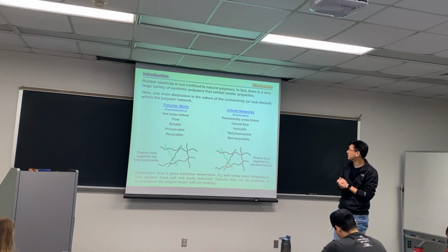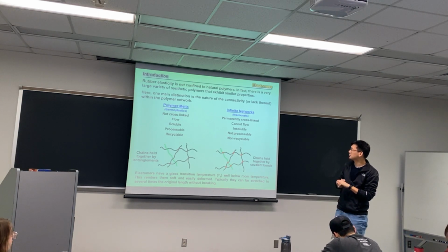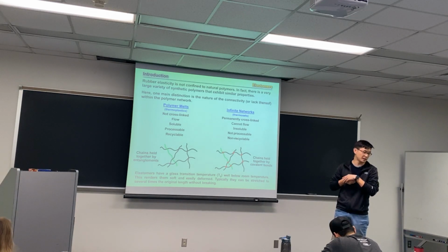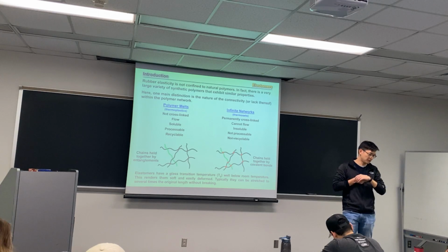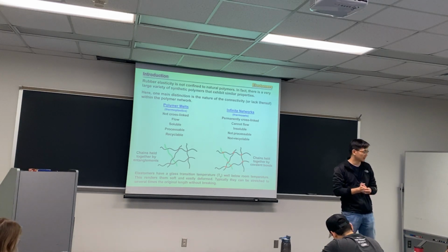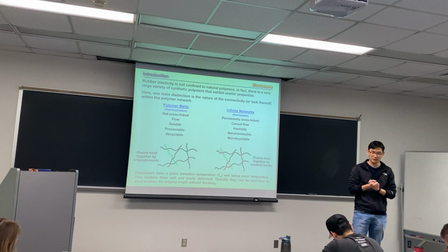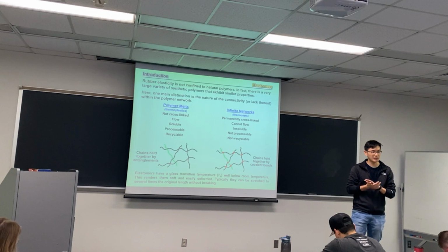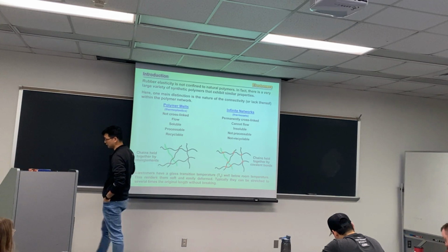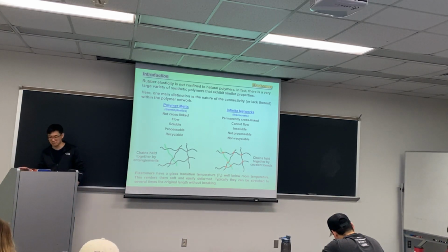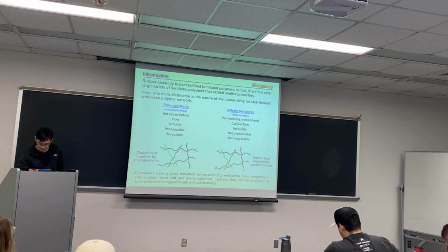And this is called a thermoplastic elastomer. It can be moved and changed at higher temperature. In other words, if you heat it above the glass transition temperature of polystyrene, now your network starts to be flowable or movable again, which helps you process the material. But if you cool it down again to room temperature, the polystyrene becomes glassy again and it won't move. That is what we are trying to show here. Of course, entanglement will play a role, but it will only make your material viscoelastic. Okay?